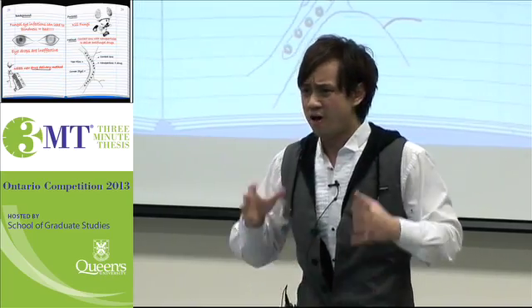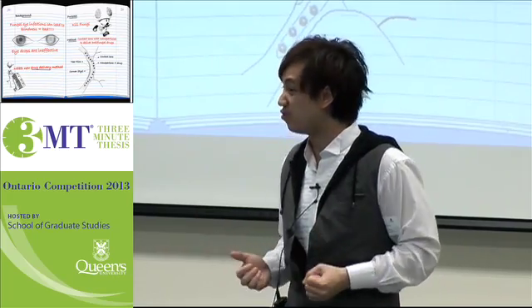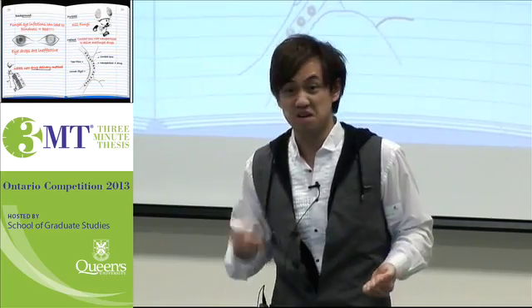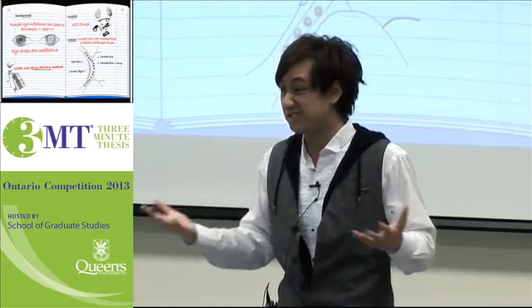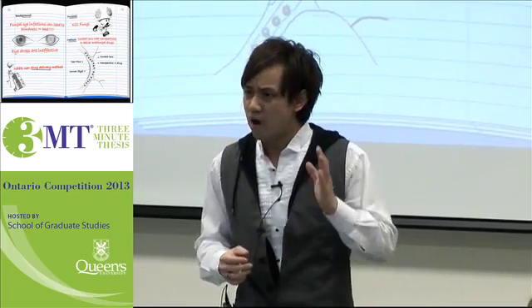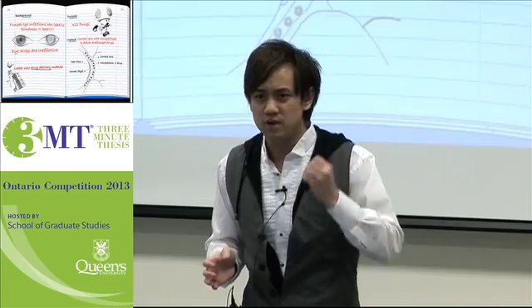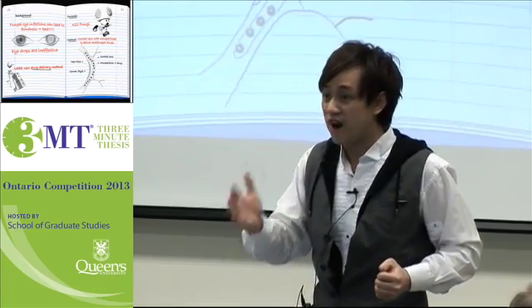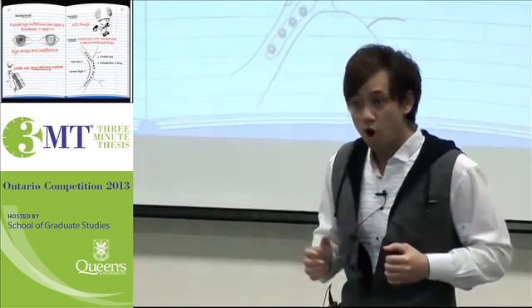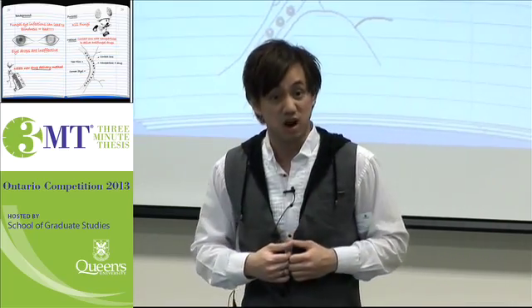The real challenge comes down to how to enable these contact lenses to continuously provide drugs over several days to even a couple of weeks. This way, all you would have to do is use one or two contact lenses containing drugs to treat a fungal eye infection. To achieve this, I've modified the ratios of the individual components that make up a contact lens to design a material capable of providing continuous drug release. To further improve this, I've used nanoparticles to first package my drugs into capsules before loading them onto a contact lens.